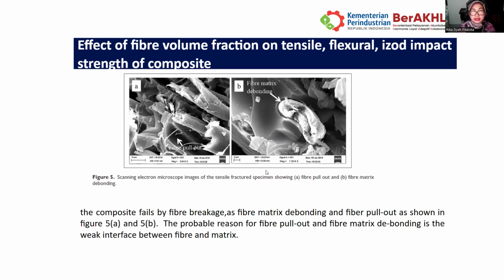And then we come to the overview, or the look, of the image after the process of adding epoxy resin to the tear-ragged fibers from waste garments or textiles into shoddy. This scanning electron image shows the tensile fracture specimen, and point A shows a poor look, with fiber pull out and fiber matrix debonding. So the composite fails through fiber breakage, fiber matrix debonding and fiber pull out, as shown in pictures 5A and 5B.